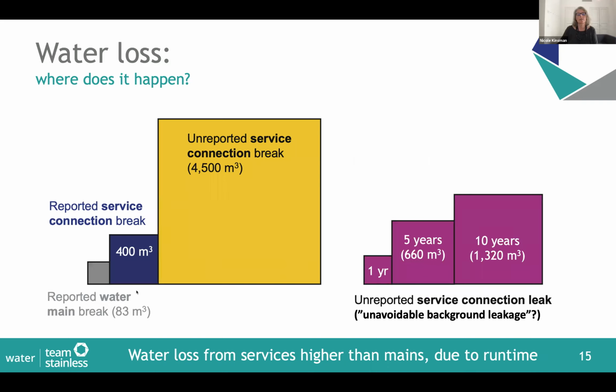So just to visualize what I just mentioned, this little gray area here would be our water main break after 1 day. Here we have the reported service connection break, which may take 16 days to fix. And this is how much water is lost, graphically representing the volume, if you have a 6 months running service connection break. And here I put down this unavoidable background leakage for a year. If it's 15 liters an hour, this is how much comes out of the system. In 5 years, this much. In 10 years, this much. And who knows how many thousands there are in a system. So the water loss from services is most certainly higher than from mains, mostly due to the runtime. That's the big difference.